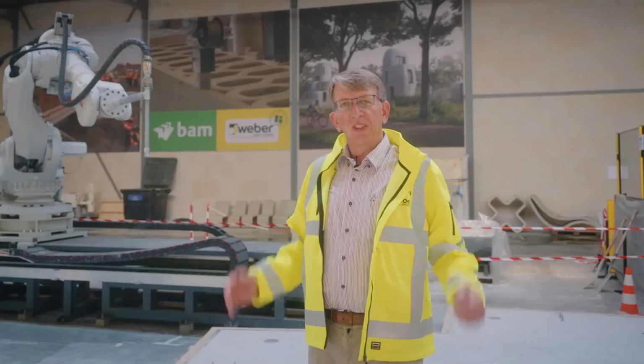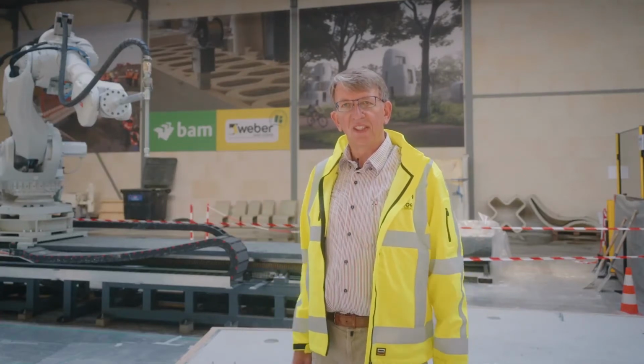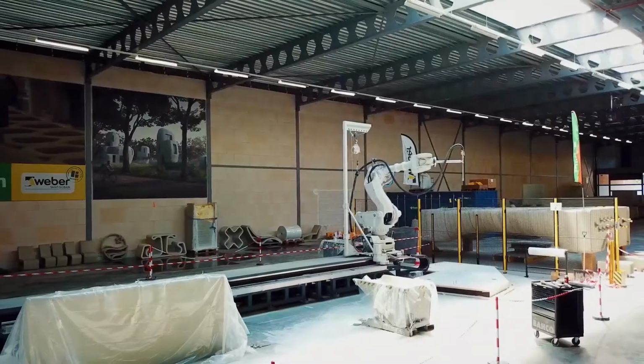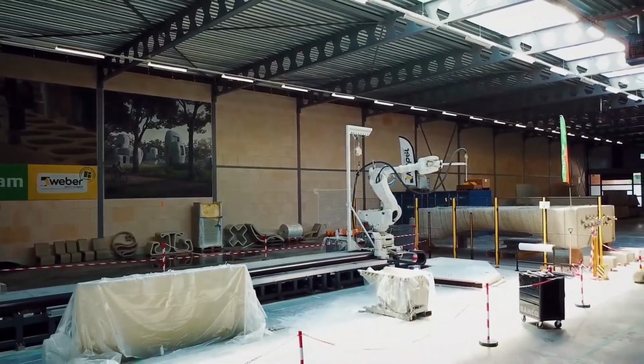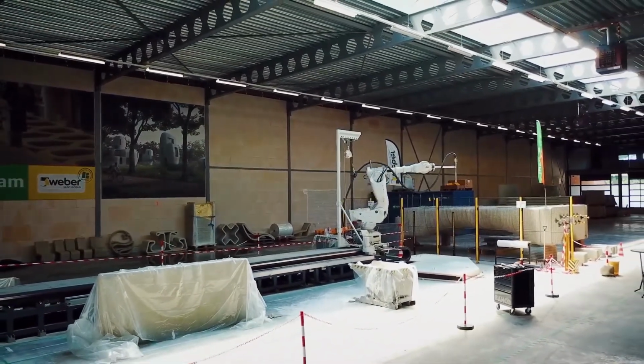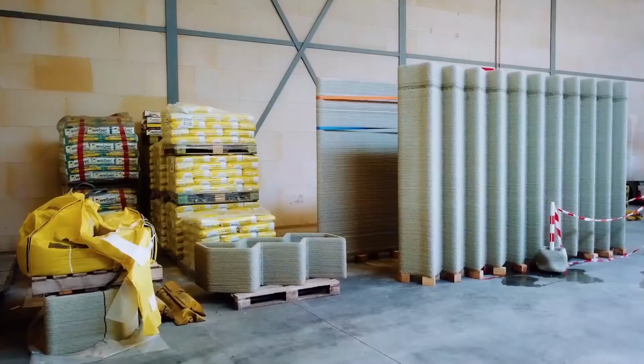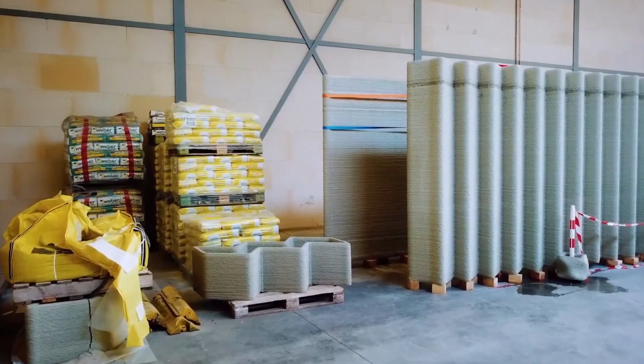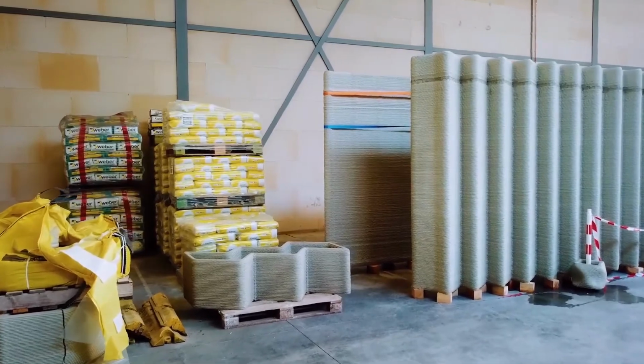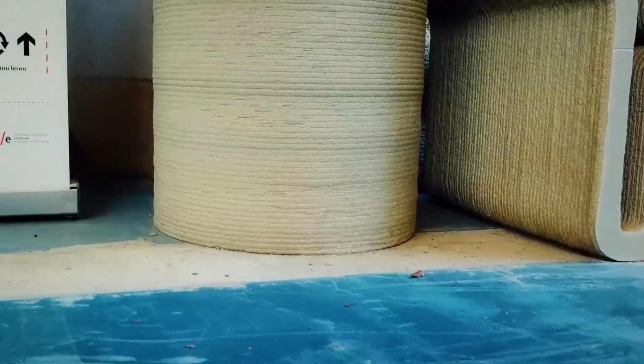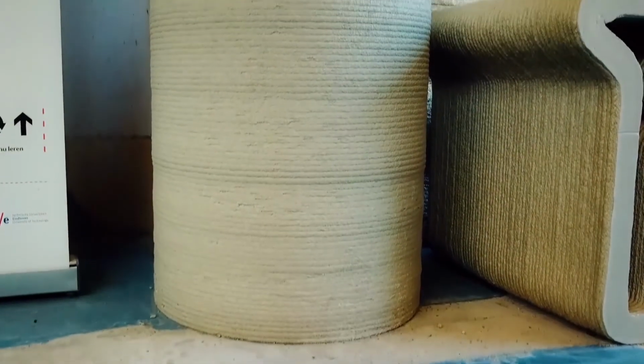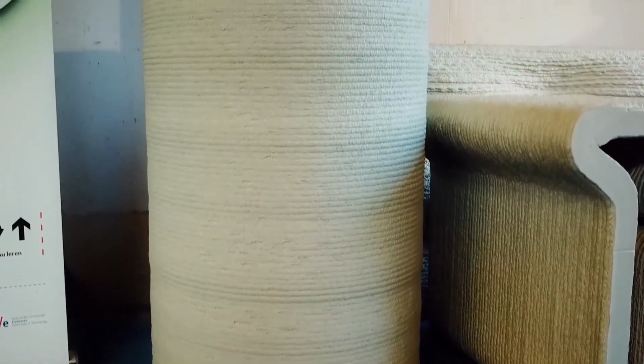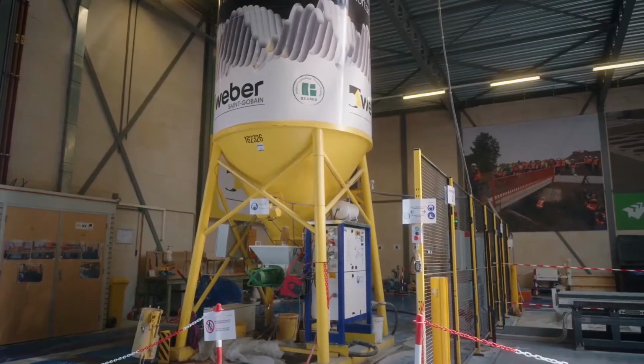The answer to solving the challenges is having a robust system. Robust with regard to the printing system, so the mixing, the pumping, the robot, but also a robust system regarding the mortar. With regard to the mortar, we have decided in our product development to stay with ordinary Portland cement as the binder. The drawback of an OPC system is that you have to find a way of being able to stack layers on layers without the bottom layer giving way when you put on a next layer on top. This problem has been solved to make sure that we have modified the rheology so that we get thixotropic characteristics in our mortar.